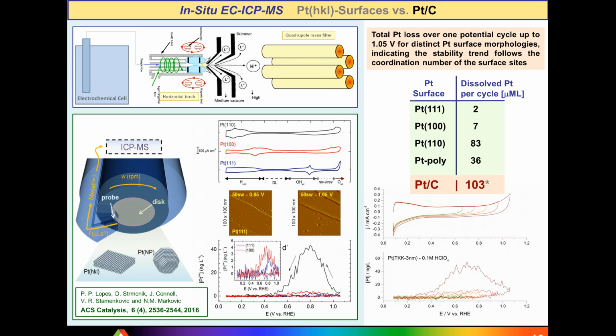Well, if you take a look at what is going on with platinum carbon catalyst, which was treated in the same way as I explained here, it is well known that we can use platinum carbon catalyst, deposit it on rotating disk electrode, and then we can observe the amount of dissolved platinum. So this is really substantial, and it goes even beyond the most unstable surface such as 110, which is in some way not surprising considering small particles. In fact, they are very rich in edges and corners. In other words, surface sites with extremely low coordination number. And those atoms are the most sensitive to dissolution.